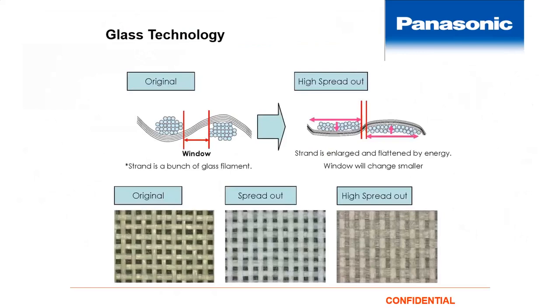So if we just compare, and these may be review, the standard glass that is not spread has the filaments grouped together in a bundle, and it forms kind of a circular pattern, and it shows the gaps here as a window. So there's a gap between the bundles. The spread glass spreads out those filaments and closes in the window, making it less visible. And from the top view, these windows on the original would be filled with resin, whereas with the high spread glasses, there are no windows, there are no gaps. And so that ends up having a more uniform effect.